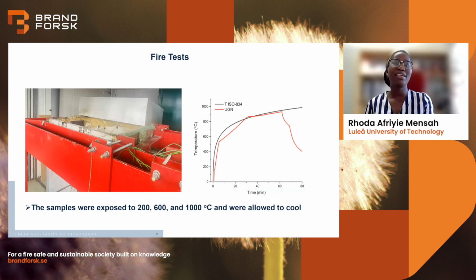So after curing, we did the fire test. In this fire test, we used a fire furnace at the Fire Engineering Protection Lab in LTU. This particular furnace follows the fire curve, the ISO 834 curve, as shown in the figure on the right. For this experiment, we arranged the samples inside the oven, and we fitted the lid of the oven to prevent any heat losses. The samples were exposed to 200, 600, and 1,000 degrees Celsius. After that, we allowed them to cool before we carried on with the other tests.